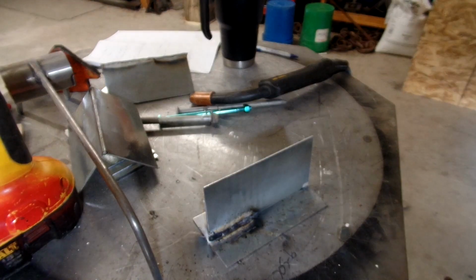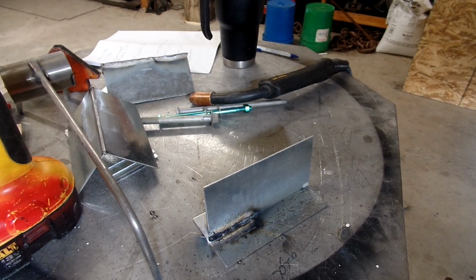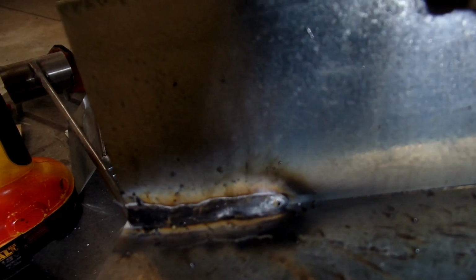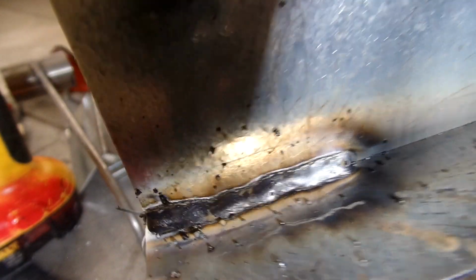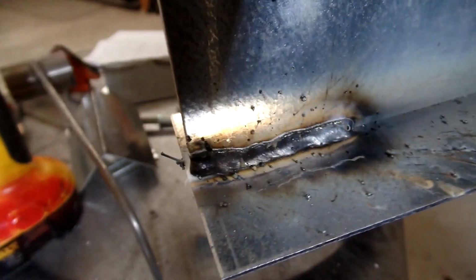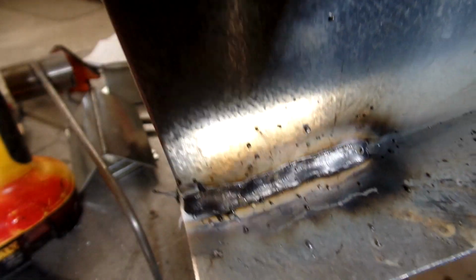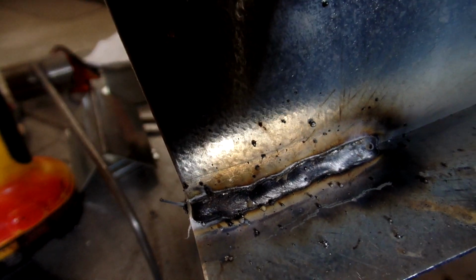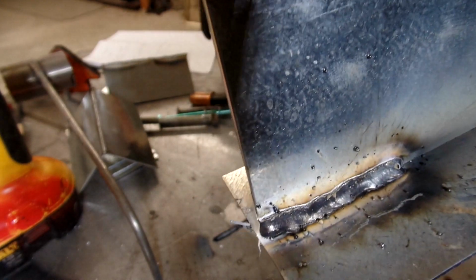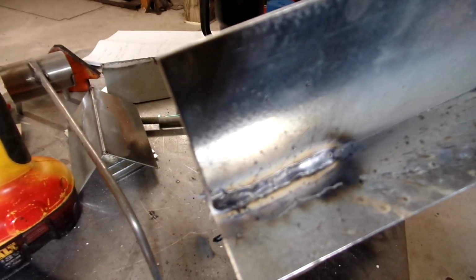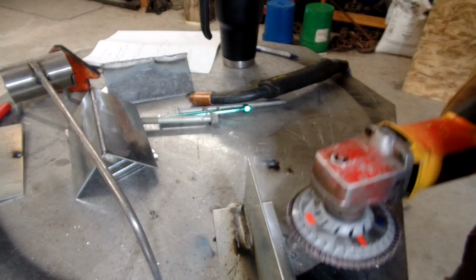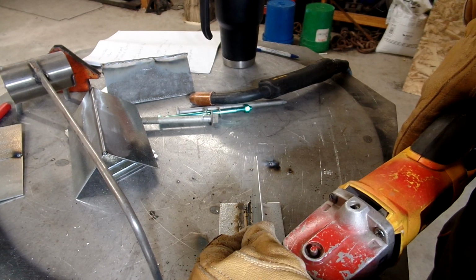Okay, you notice the excessive amount of spatter? The little pinhole in the crater there? That is galvanized. That's because you're burning off a coating before the weld gets to the base metal. So if you want to fix that, and you don't want it to be as bad, obviously, if you can and within spec, grind it out.